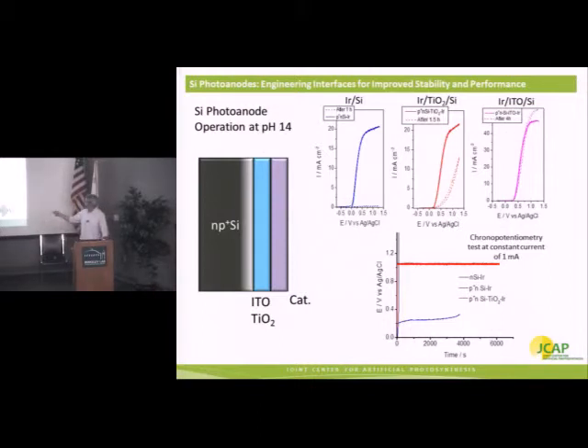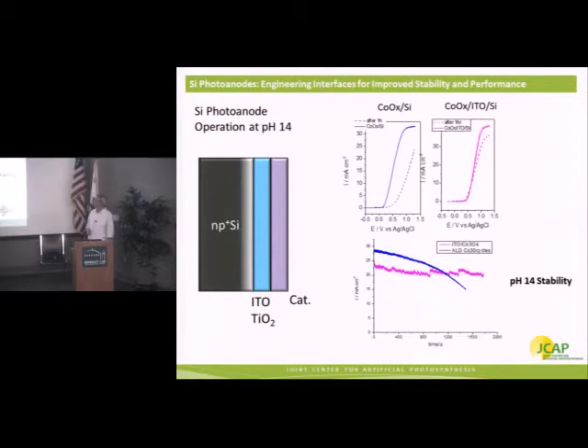For the p-n junction silicon TiO2 iridium construct, it's much more stable. You see this is a completely horizontal line, and that's for this case, not even for the case with the ITO. The one thing that you may notice here is that you do require a higher potential to be applied in order to achieve this 1 milliamp current density. So there's room for improvement. That's the takeaway from that. The other takeaway is that that was all done with iridium, so let's maybe move on to something that's earth abundant. So we've done the same thing with cobalt oxide.